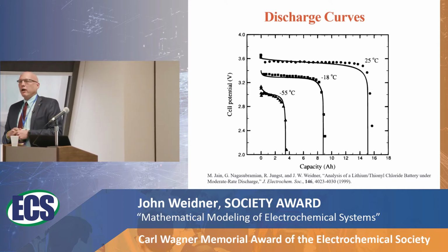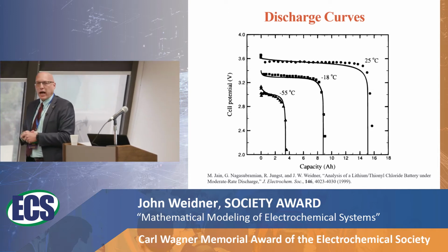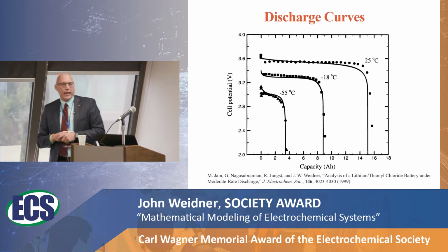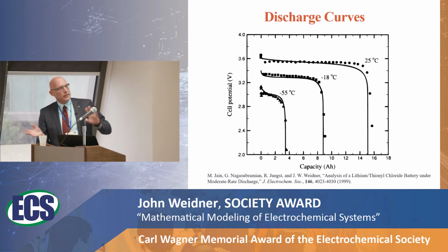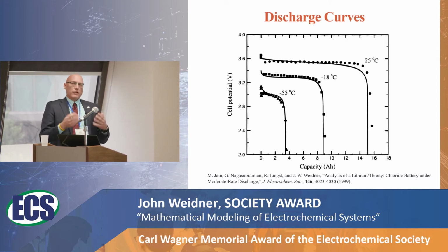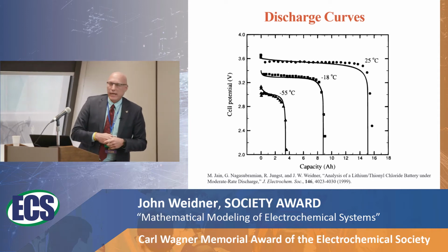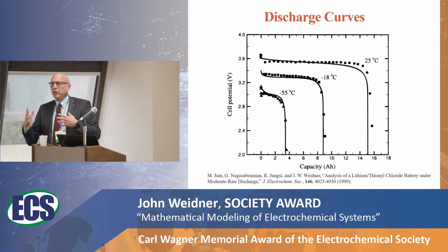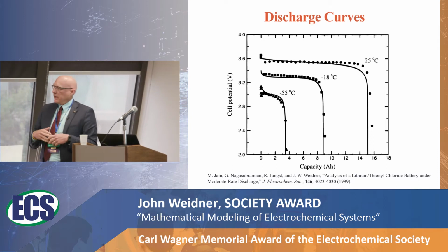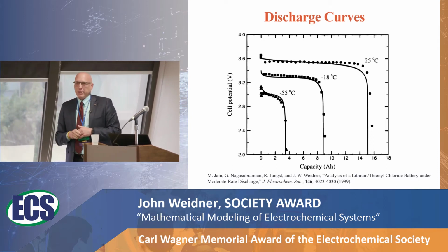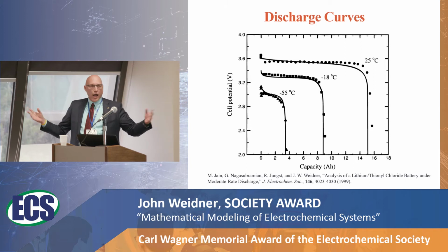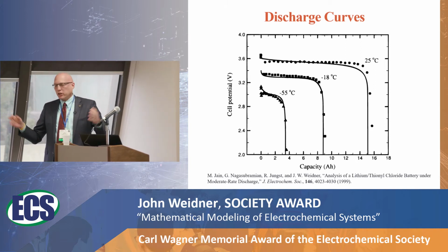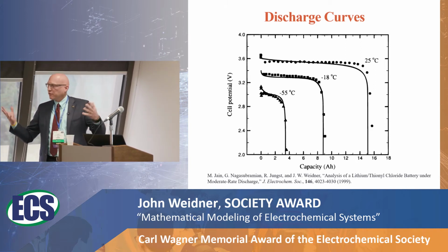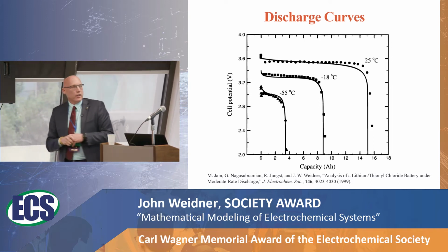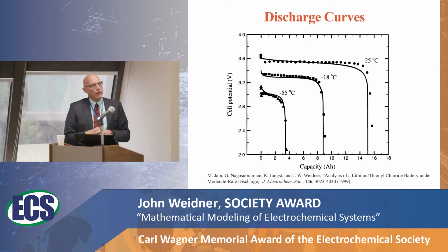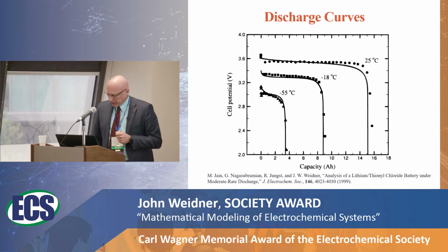But here's an example at the end of the day, where you've gone into the lab, or they did a lot of work on transport and kinetics in individual cell studies. You put that into the model and you get some good agreement between the experimental data and the model. You feel good that you've got a lot of the physics in there. There's still some parameter estimation that you're doing, but again, you're doing it over a very wide range of discharge currents, temperatures, and so on. And so again, you feel like you've got most of the physics, although maybe not all of it in there, and it gives you some gratification that you can maybe get some understanding of what's going on.